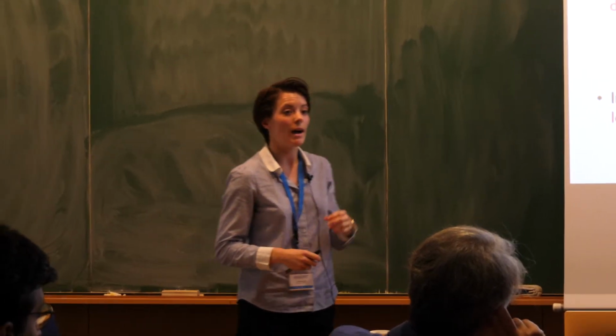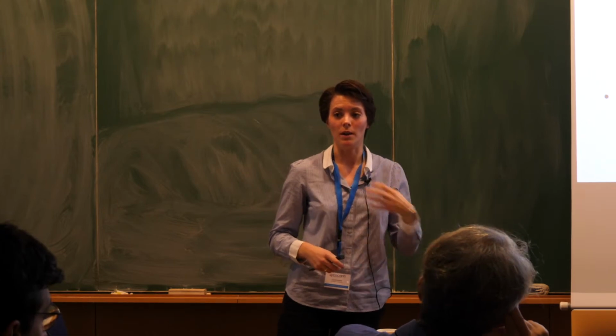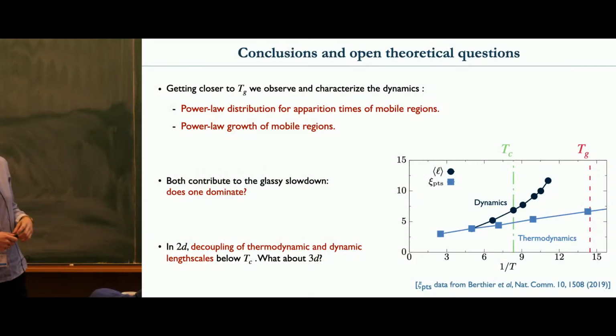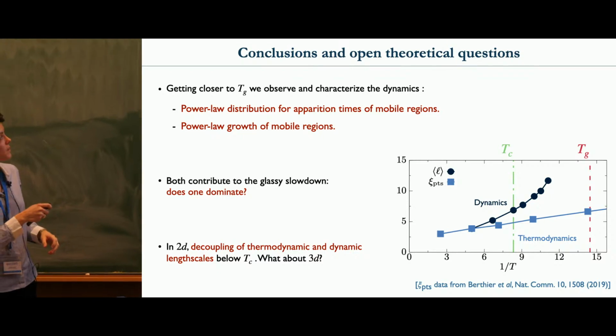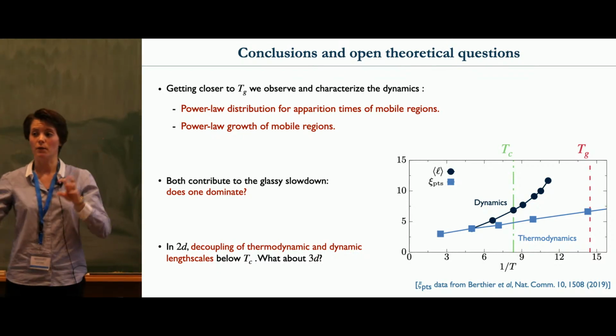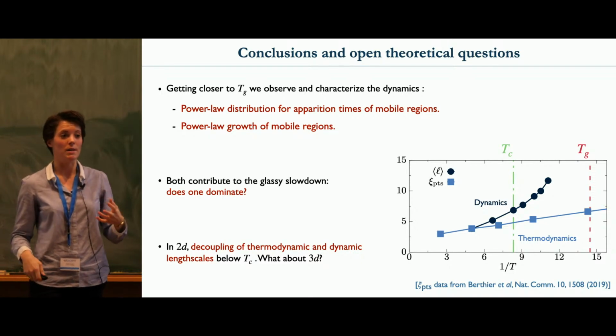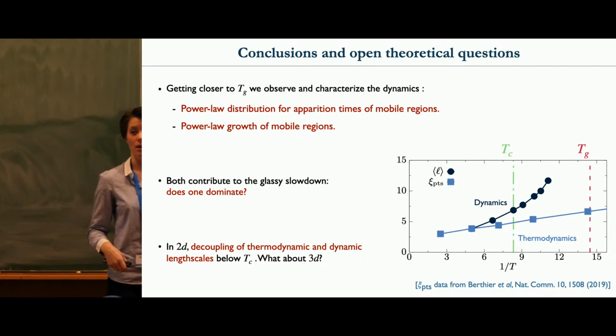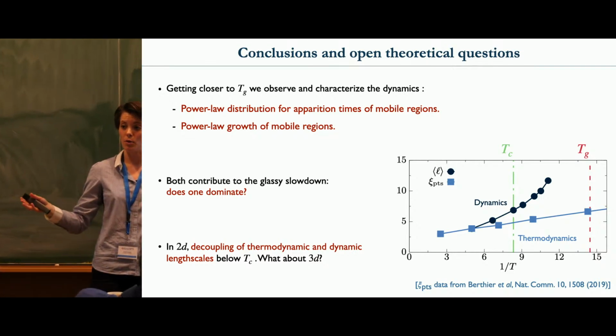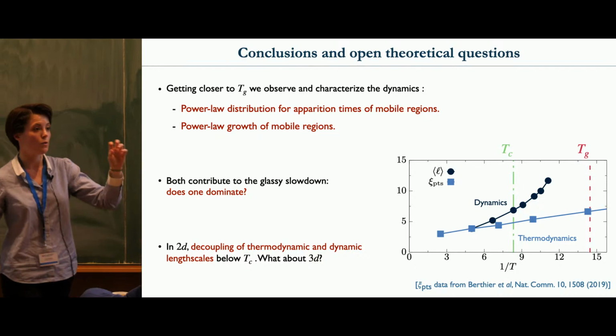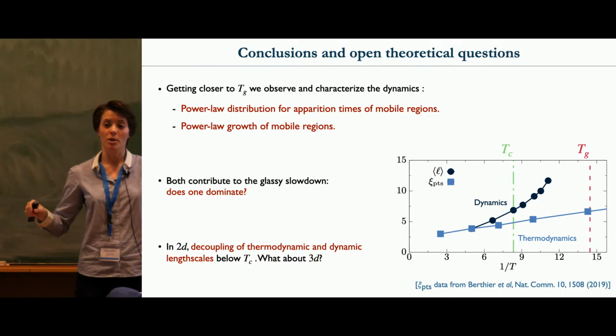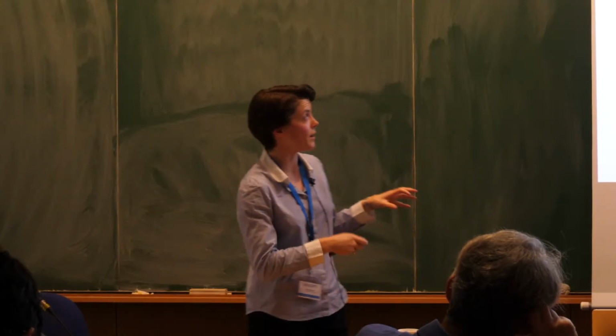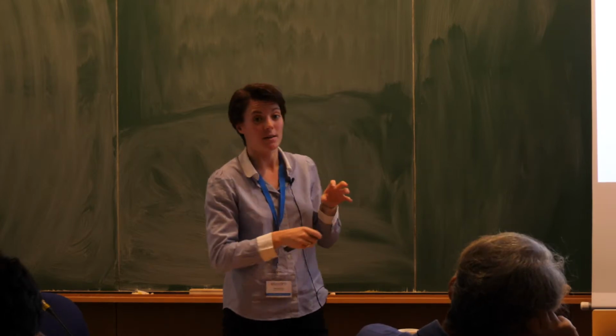So the conclusion of this work and the open theoretical questions are the following. As we go to lower and lower temperatures, going to the experimental glass transition in simulations, we observe two things. The first is that there is a distribution for the apparition of these mobile regions that we can measure directly. We see that they appear on timescales that are power law distributed, so there's a huge distribution of timescale for these mobile clusters to appear. And then at later time, each region grows in time, and this growth itself is increasingly slow and very, very slow. And we characterize this by a power law and probably even a logarithmic growth.